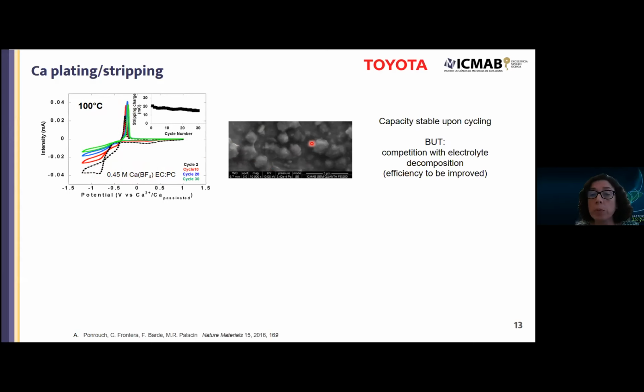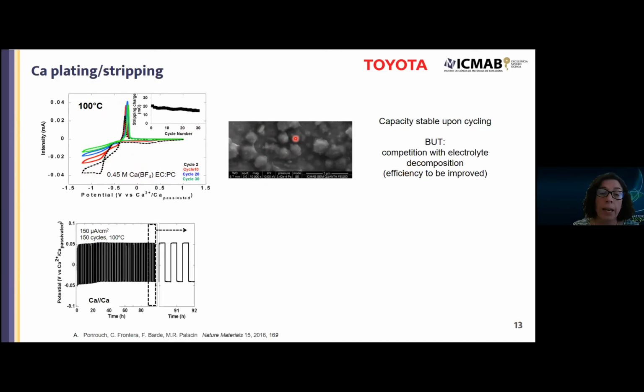This is the calcium deposits. And of course, this is far from ideal because the efficiency is not very good. There is quite a lot of electrolyte decomposition, but still we were able to see by X-ray diffraction that this is calcium metal.